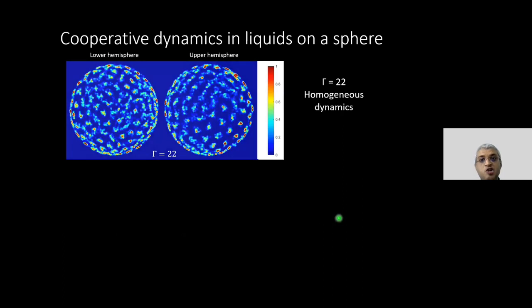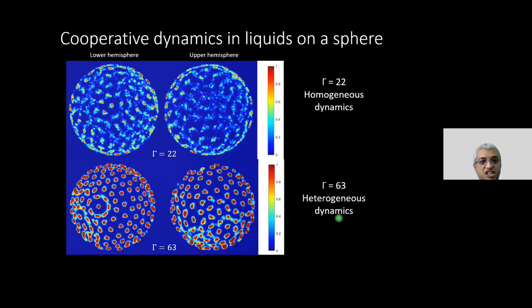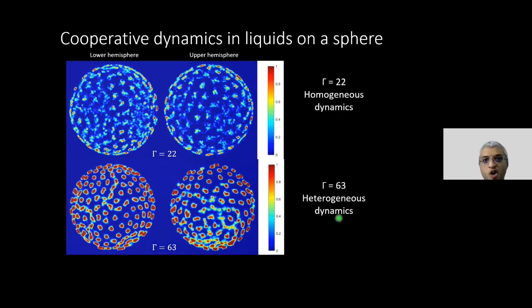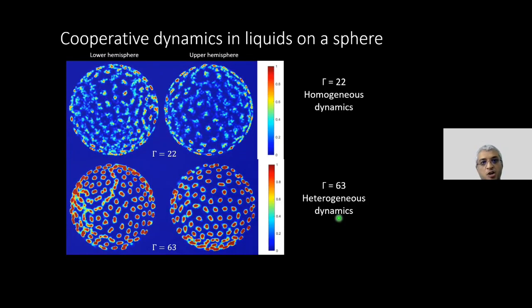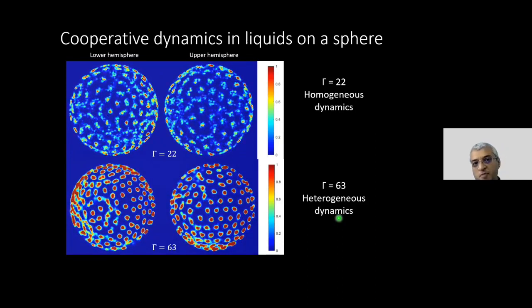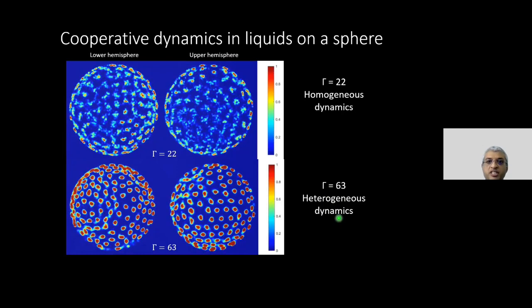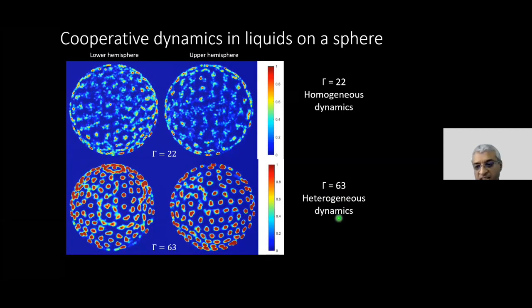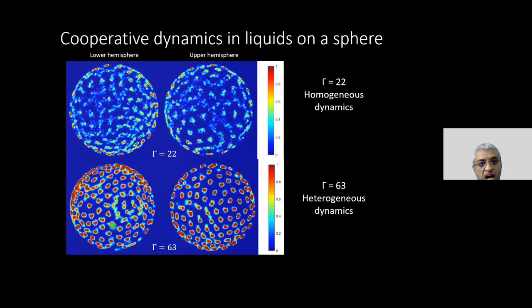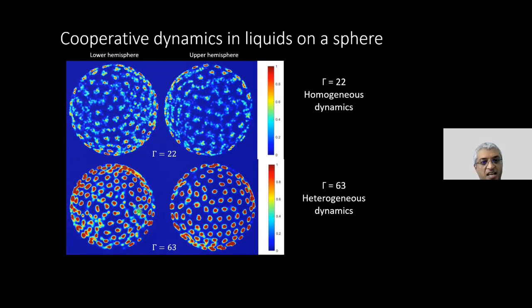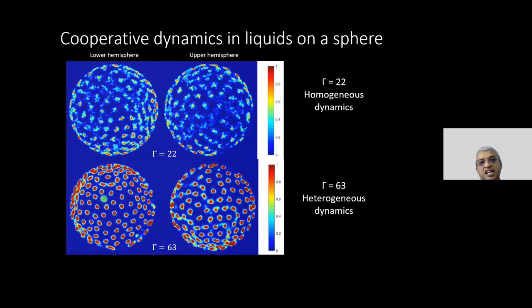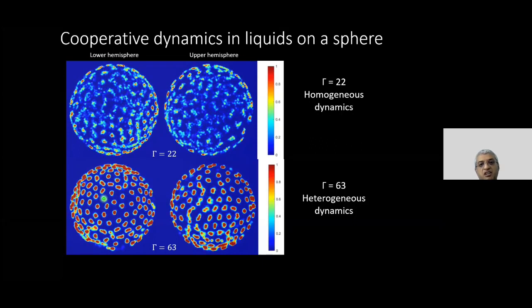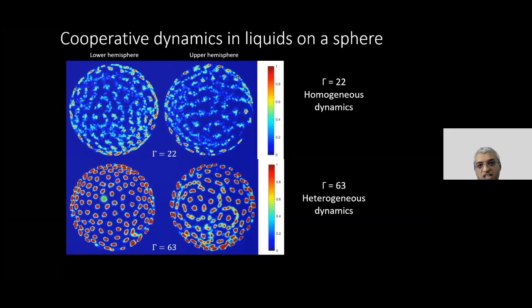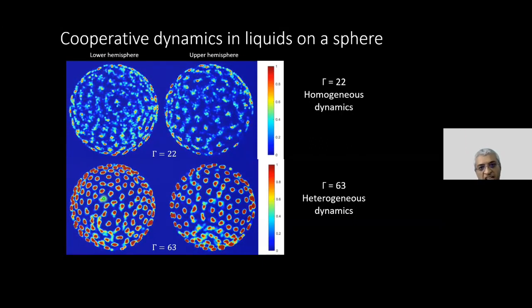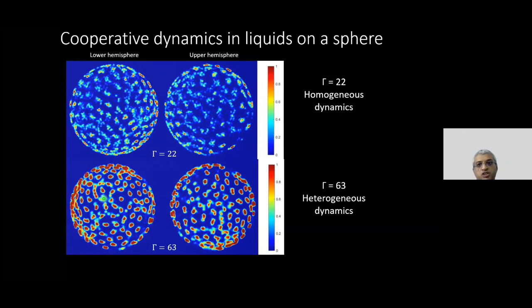What I can do is cut to the chase and tell you what happens to the cooperative dynamics on the surface of a sphere. Just like I showed you in my devitrification data, I'm showing you time-averaged snapshots of particle mobilities, and you will see that particles are evolving in a highly cooperative manner. Now we can ask whether in this system, just like we found in flat space where the dynamical heterogeneities were changing shape, do these also change shape?